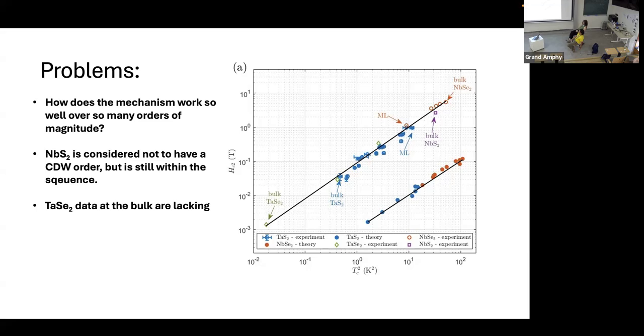If you go from thick to thin, the screening would change, also the environment. But here you have carrier mobility also, and if it's metallic, carriers cannot move. But say Tc has this mu star, which goes into the exponent. So how exactly does screening affect mu star in the BCS theory? It comes from the Anderson-Morel pseudopotential, and this depends on the exact dependence on the interactions. It's usually done for the 3D theory, but in the 2D case you have a sort of different screening.